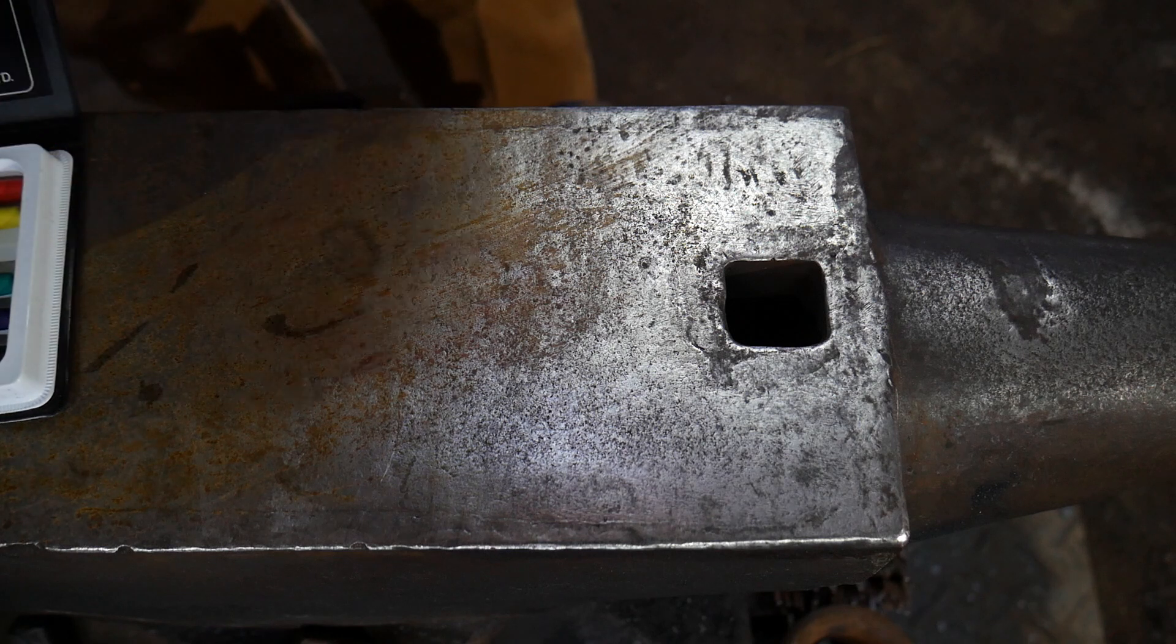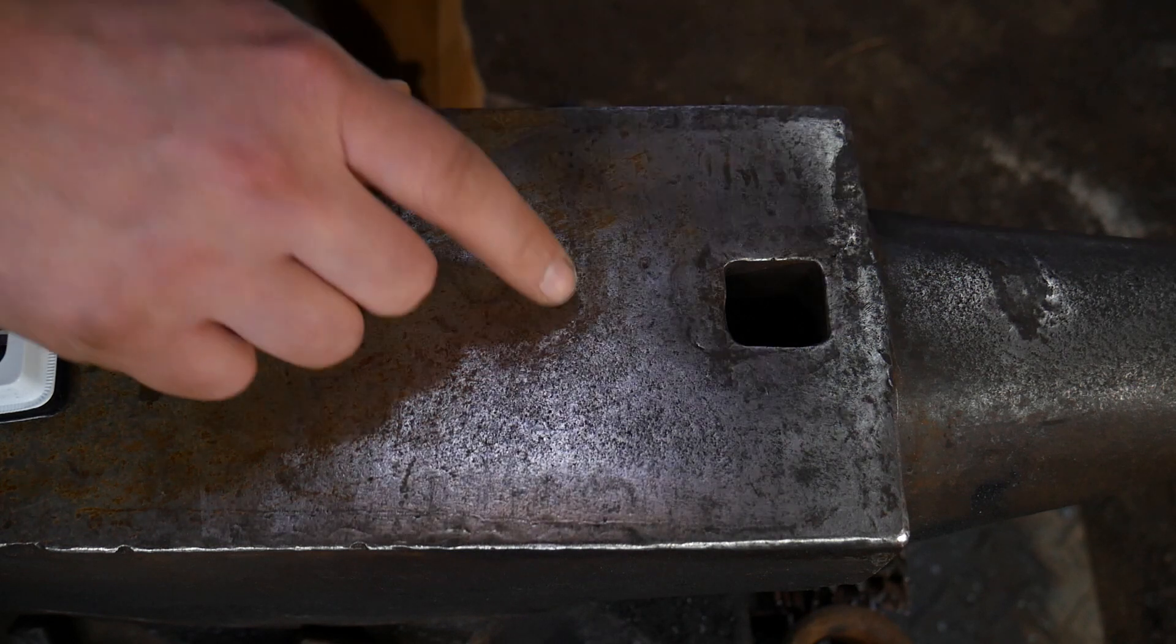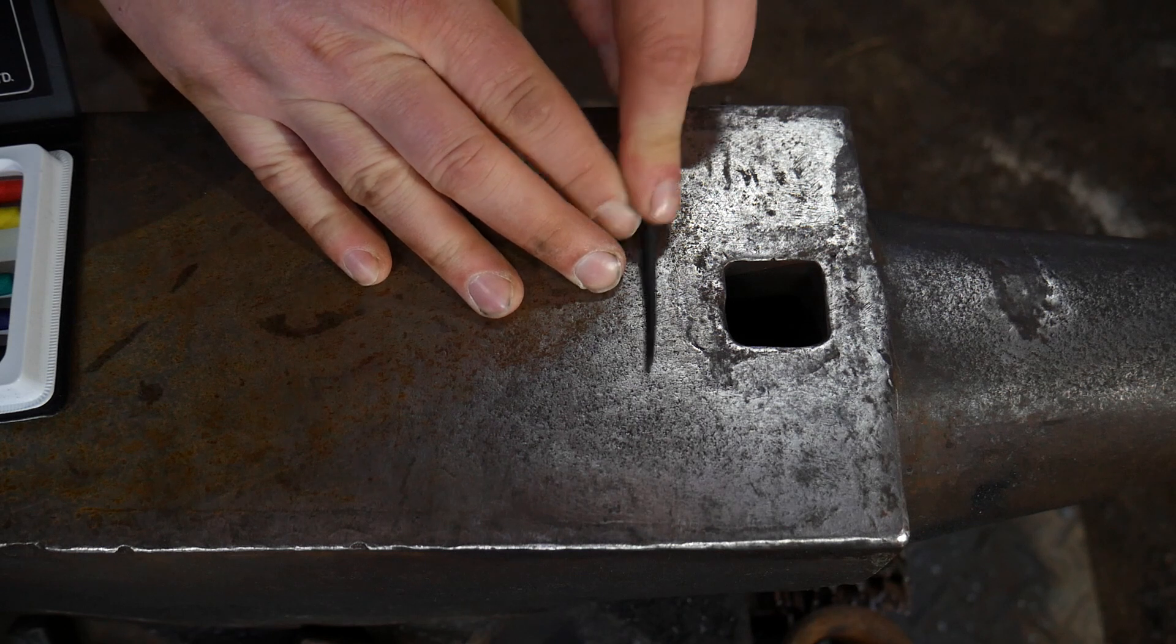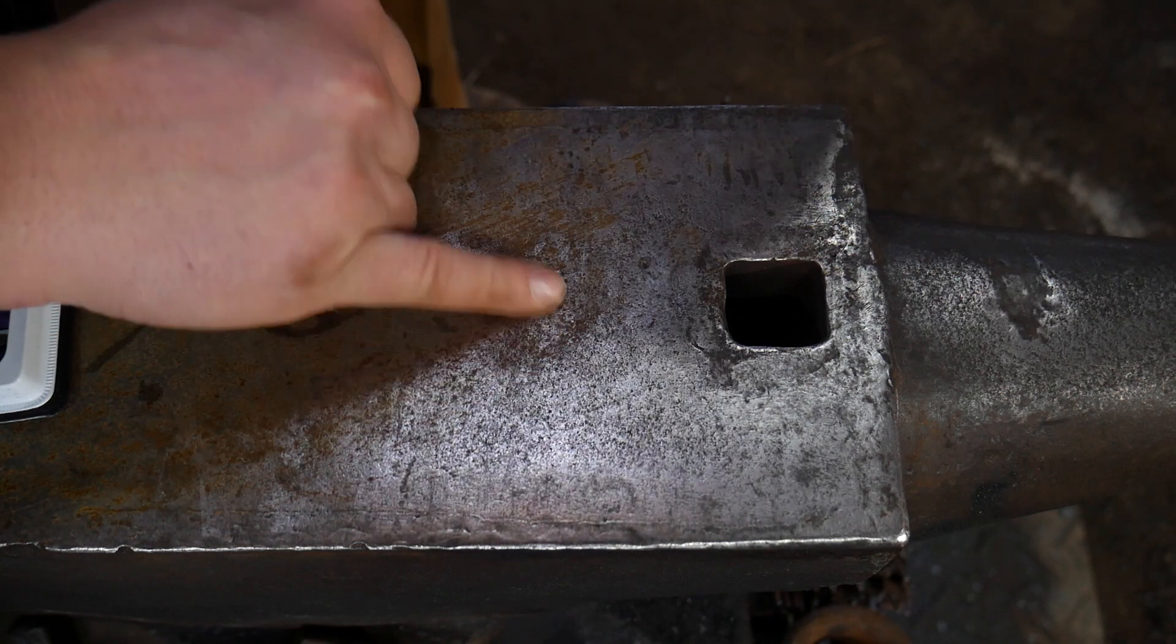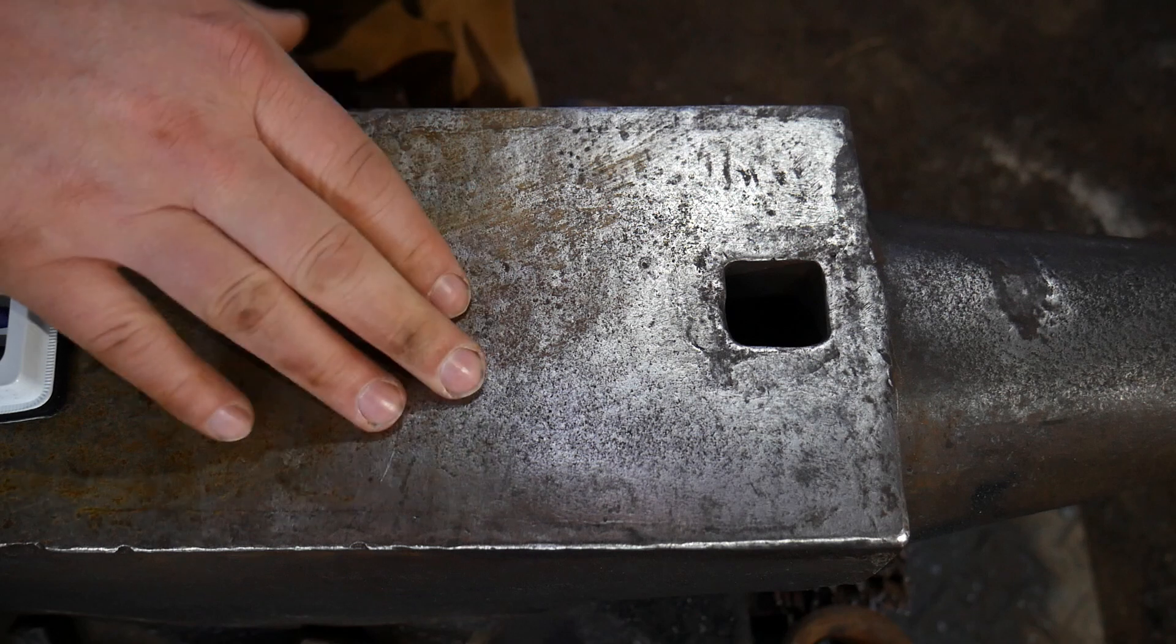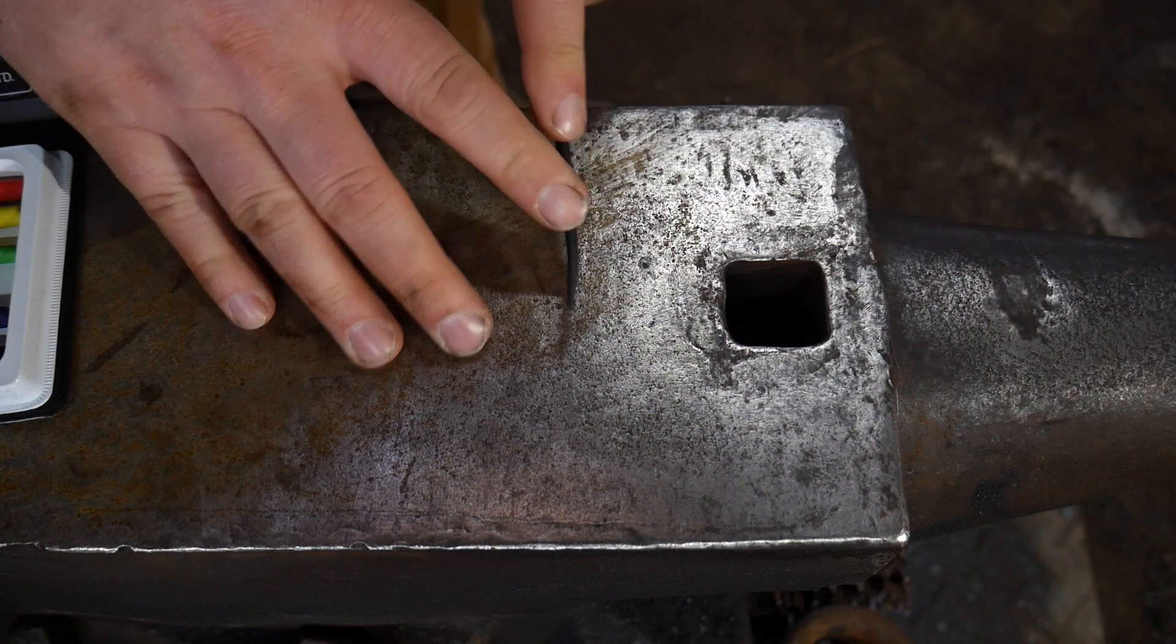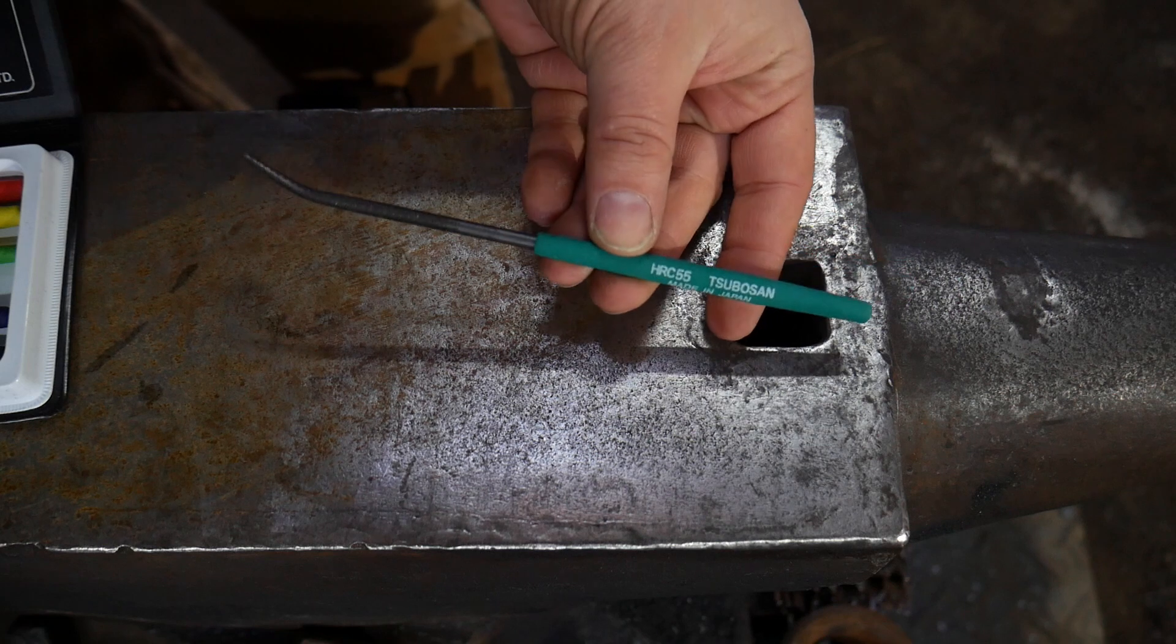We'll move up to 50 Rockwell. We're going to do the same test. That felt a little bit more grippy and it just started to kind of put a little bit of a mark there. Come over here to the rusty area. It's just removing a little bit of rust, but other than that mostly unscathed. So this is going to fall right between where I figured it was going to, between 50 and 55 Rockwell most likely. Yeah, and now that bites.